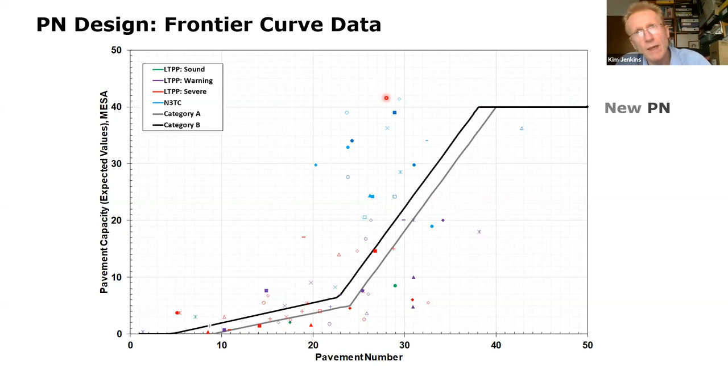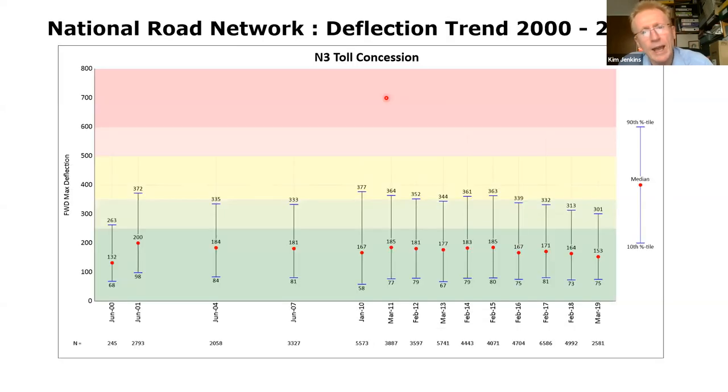It doesn't miss that maintenance that should happen this year, but then is pushed out till next year. No, it happens. And if that happens, here's an example: it's 20 years. The data has shown that the deflections in that pavement have remained constant. The average and the maximums, there's some variability, but one would expect the maximum deflections to increase over time as the layers become damaged. But if you are really rigorous and check that the periodic maintenance is always done, this is one way to preserve a pavement. And it's something we've got to consider in terms of sustainability.